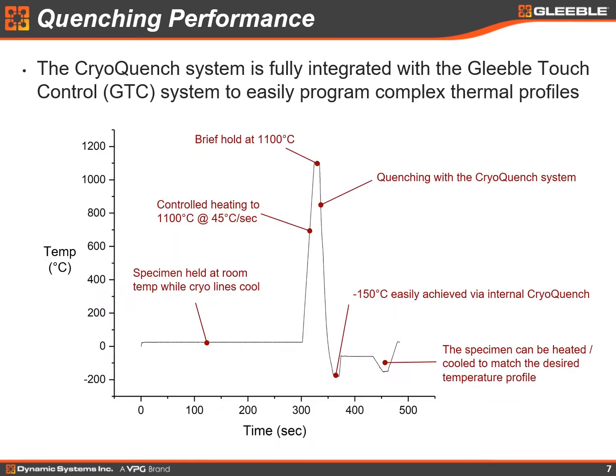Using the cryo-quench system on the ISOQ setup, it's very easy to program very complex thermal cycles both above and below room temperature, and essentially simulate any process that you may wish to simulate. This example here just shows a sample being held at basically room temperature while the cryogenic lines are cooled, heated at 45 degrees C per second up to 1100 C, cryogenically quenched down to minus 150 C, brought back up to an intermediate cryogenic temperature, requenched cryogenically, and then brought back to room temperature.